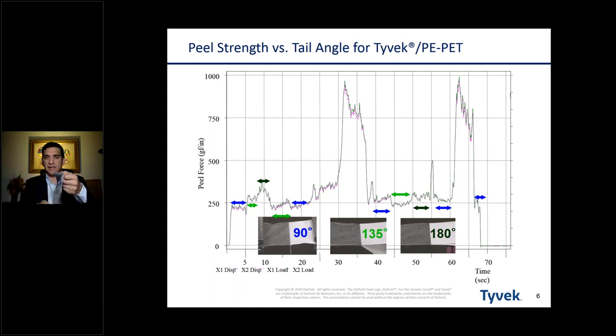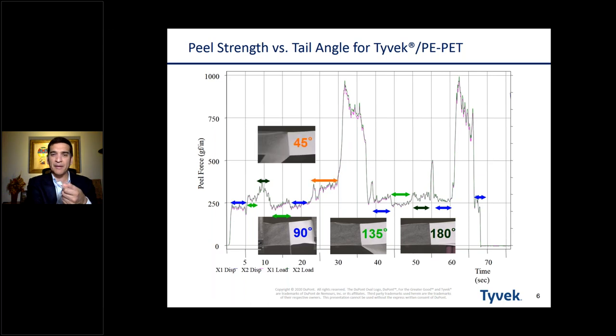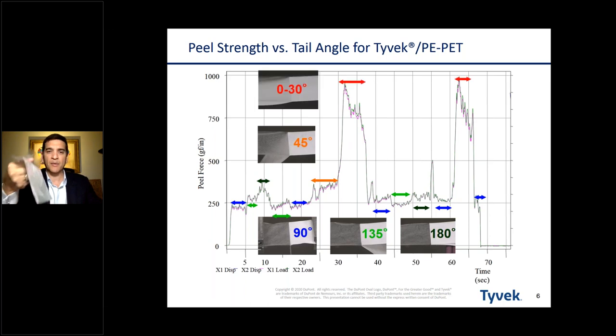So in these orientations, 90, 135, 180, you can see there's a range, but it still stays within a certain given amount of range. But here's the fun part. When we look at the 45 degree, now I'm bending back towards the film side. And when we go to 0 to 30, so when we're bending completely back on the film itself and peeling back this way, it's almost up to 1,000 compared to 250. It's a different measurement system here, but it's almost a fourfold increase if I peel it back towards the film as compared to peeling back towards the Tyvek.